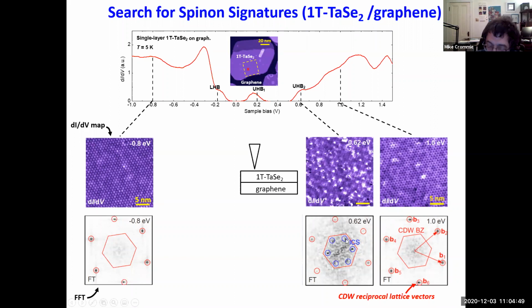And you can see them here. I've circled them in blue. If you take the Fourier transform of this image, you get these new periodicities. I call them ICS. That stands for incommensurate superstructure, or incommensurate structure, because they're incommensurate with the charge density wave. And so we get these Fourier peaks at these very specific periodicities.